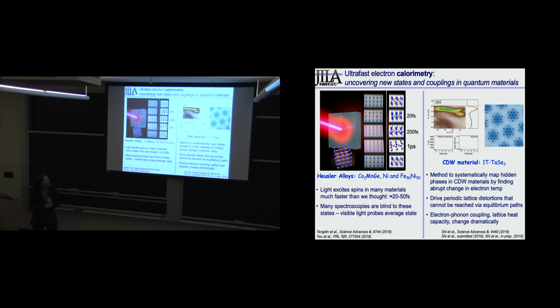And then similarly in these charge density wave materials, we think about tuning their properties with pressure or with doping normally. Turns out that if you use ultrafast light, it naturally interacts with the charge, and we're not the first to see that you can excite one of these breathing modes, that are related to the periodic lattice distortion in these charge density wave systems.